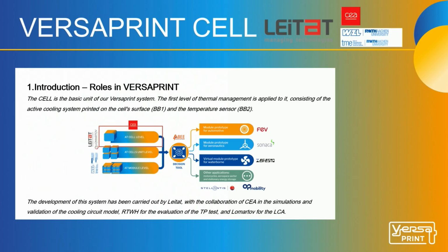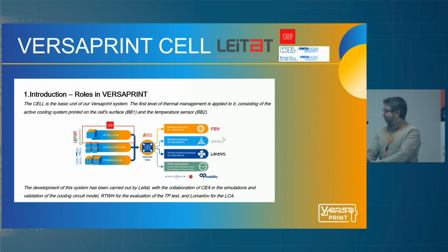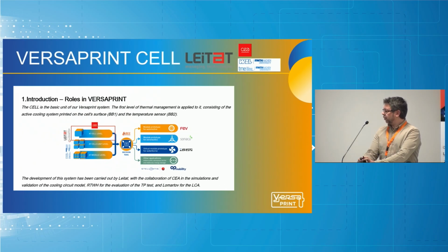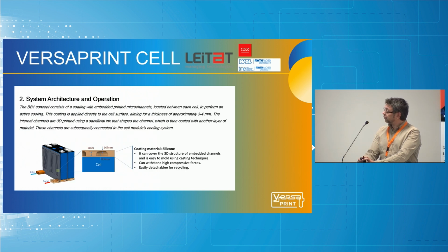This development of these systems has been carried out by LEITAT with the collaboration of CEA for the simulations and validation of this cooling circuit model, RWTH for the TP test, and Lomartov for the LCA. The concept of this BB1 consists of this coating with embedded microchannels that are located between each one of the cells in the cell unit and the module to perform this active cooling. This coating is applied directly over the cell surface, and it's aiming for a thickness around 3 or 4 millimeters.